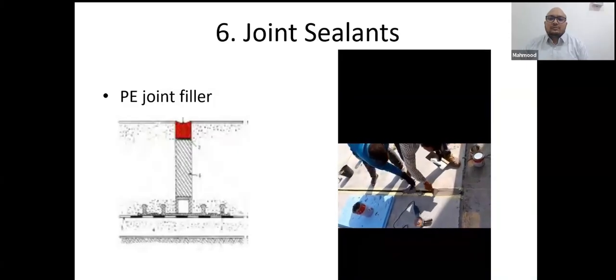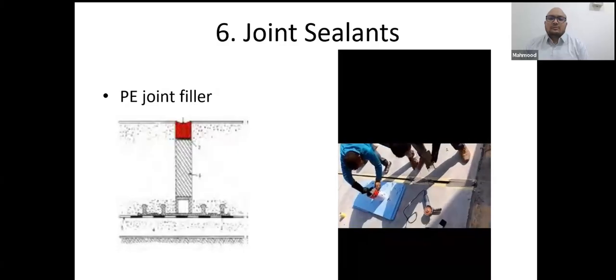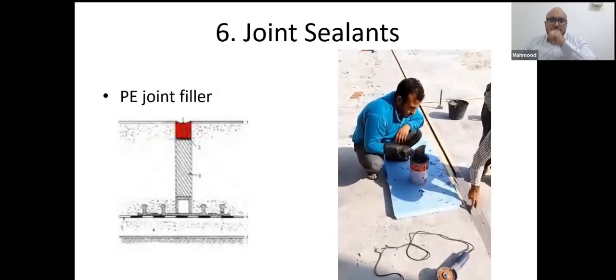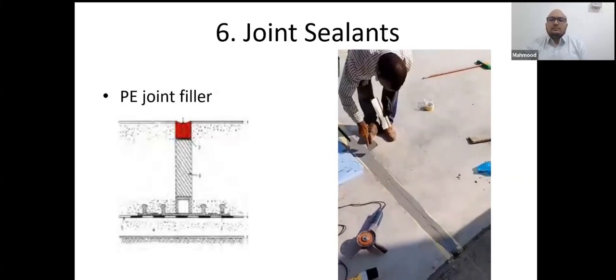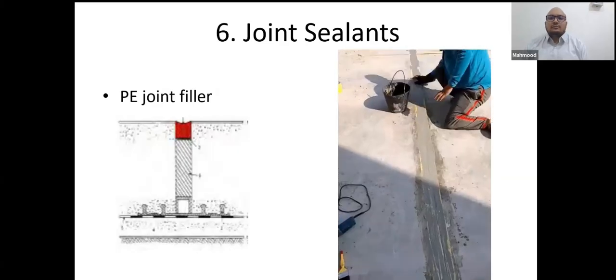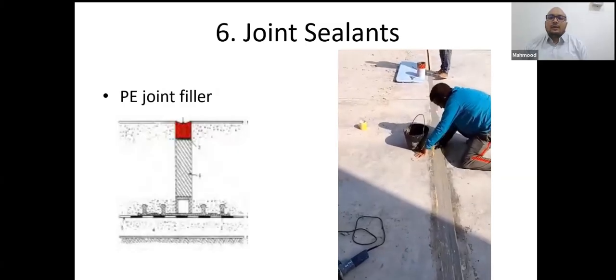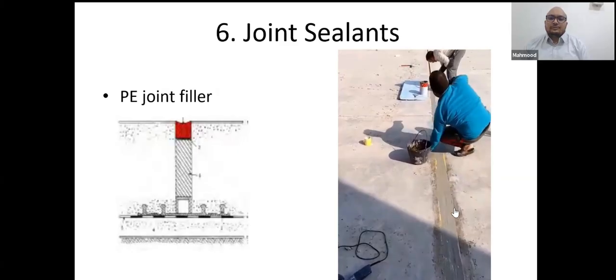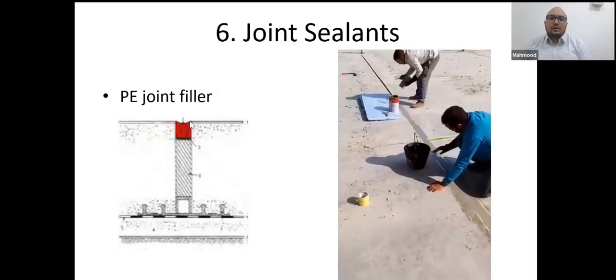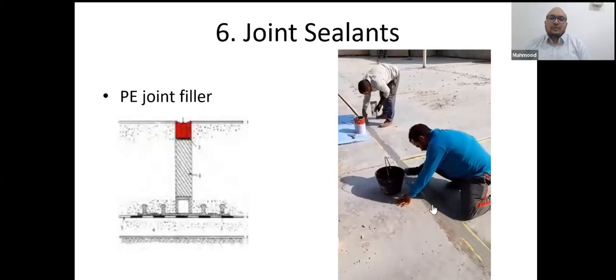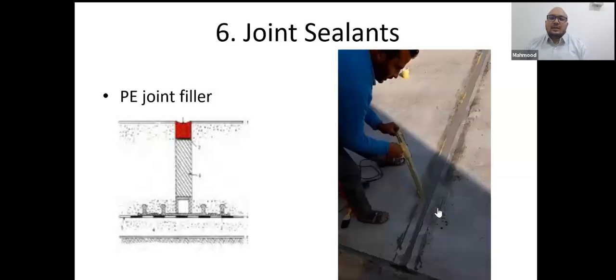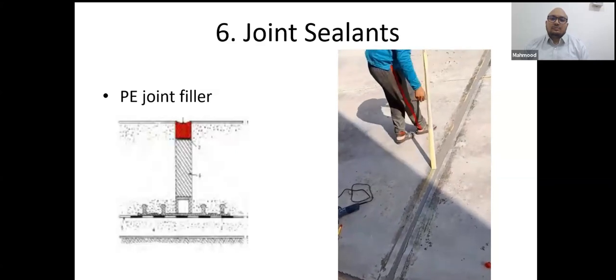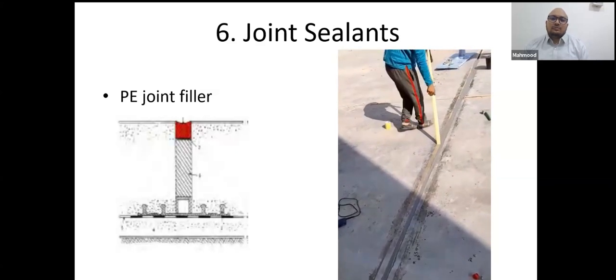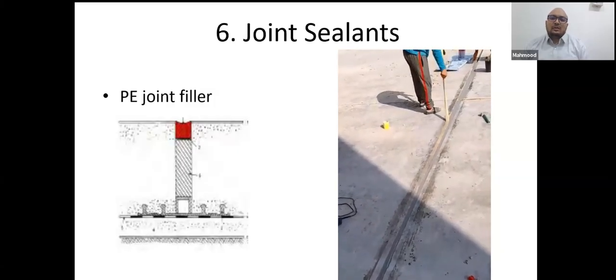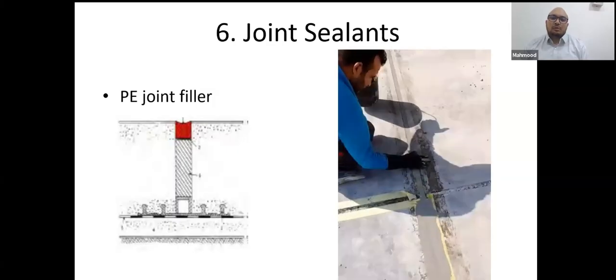They're filling it with the scraper. They're applying soapy water to make the surface smooth. To bring this curve on the drawing, they're doing it. And they're removing the masking tape. After 8 hours, it will become a very hard rubber. Polysulfide, polyurethane sealants, polyester based sealants.